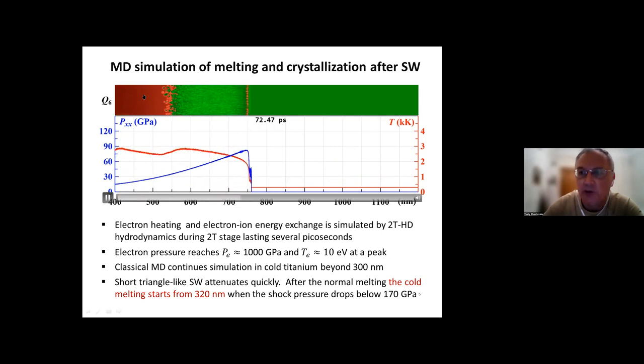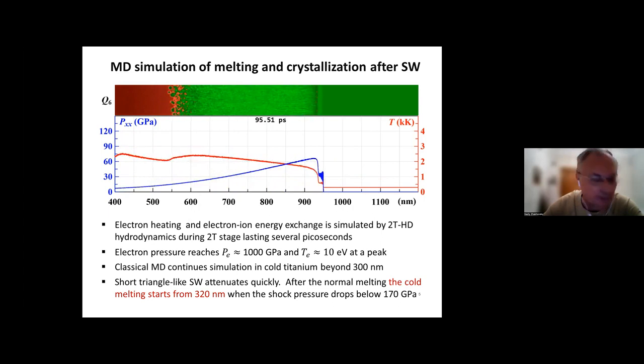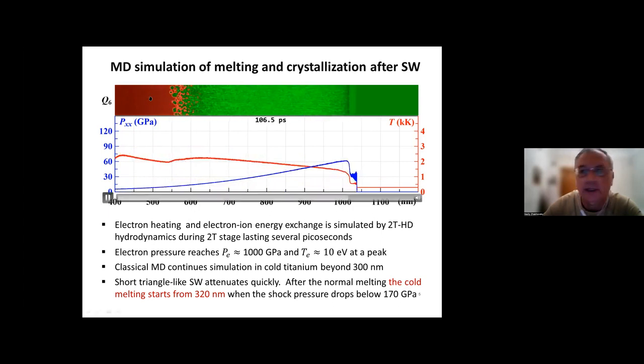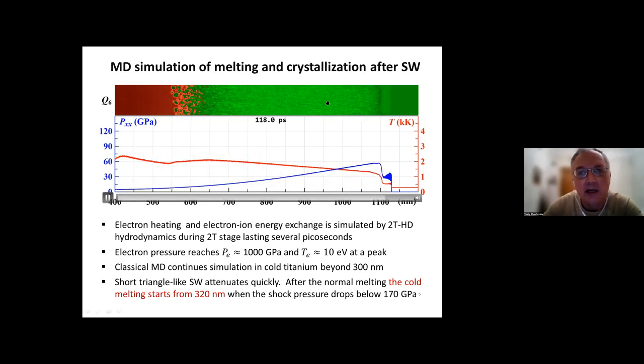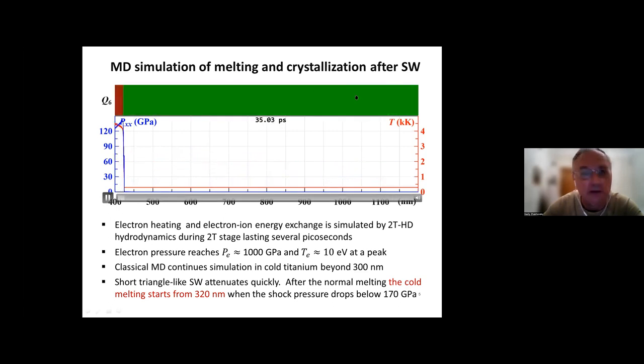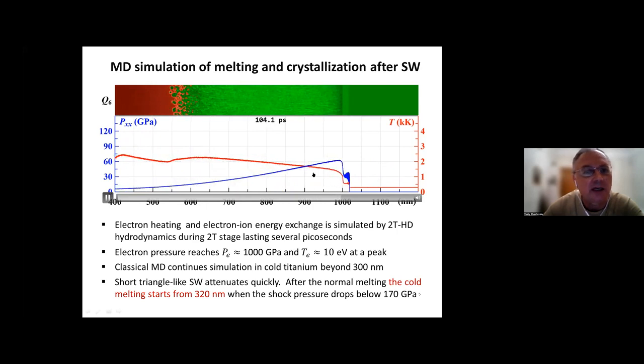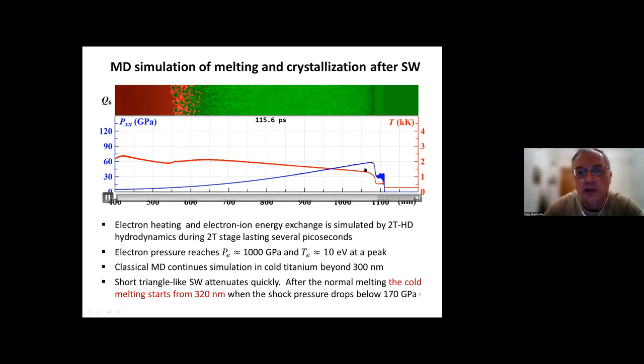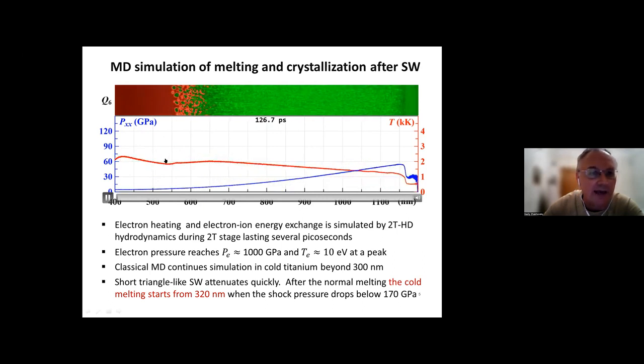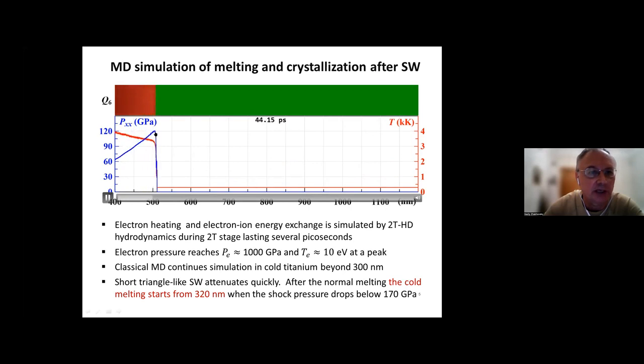It is just an atomic order parameter which indicates position, using an expansion on spherical functions of a local atomic coordinate. Green colors indicate solid phase. The shock wave, the pressure stress wave, propagates and has a triangle-like profile. It attenuates quickly because the release wave causes expansion of this wave and attenuation as well. And of course, temperature is also associated with the amplitude of the shock wave.